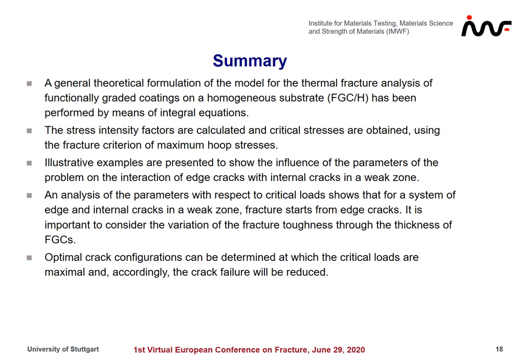Summary. A general formulation of the problem for the thermal fracture analysis of functionally graded coatings on a homogeneous substrate has been performed by means of integral equations. Stress intensity factors are calculated and critical stresses are obtained using the fracture criterion of maximum hoop stresses. Some illustrative examples are presented. Analysis of parameters with respect to critical loads shows that for a system of edge and internal cracks in a weak zone, fracture starts from edge cracks. It is important to consider the variation of fracture toughness through the thickness of functionally graded coatings. Optimal crack configuration can be determined at which the critical loads are maximum and accordingly crack failure will be reduced.